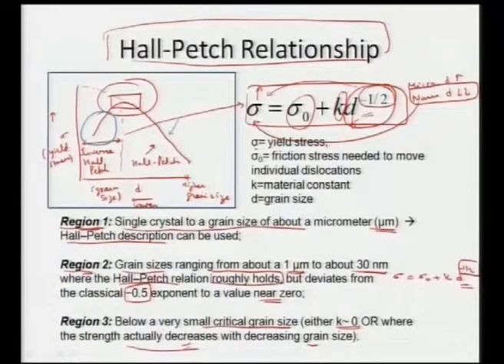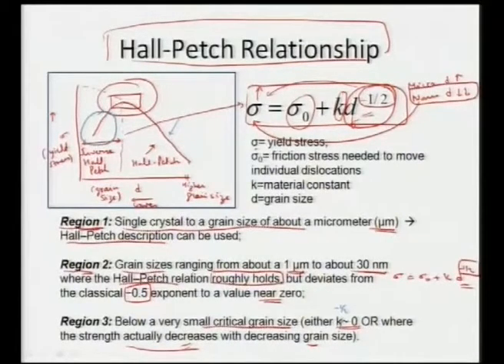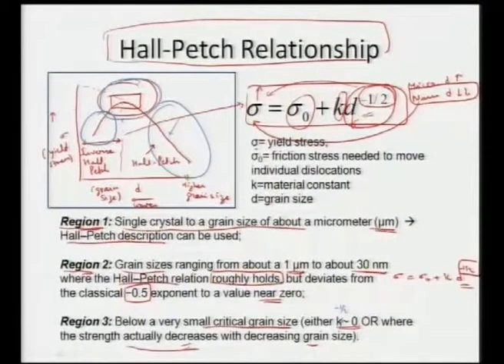In Region 1 we have very well maintenance of the Hall-Petch relationship. In Region 2, for grain sizes between 1 micrometer and 30 nanometers, the overall exponent of −0.5 is basically going to approximately 0. In Region 3 the slope itself is also going to 0 — the yield stress is decreasing as we further lower the grain size. That limit is approximately around 15 to 30 nanometers and it can depend from material to material.